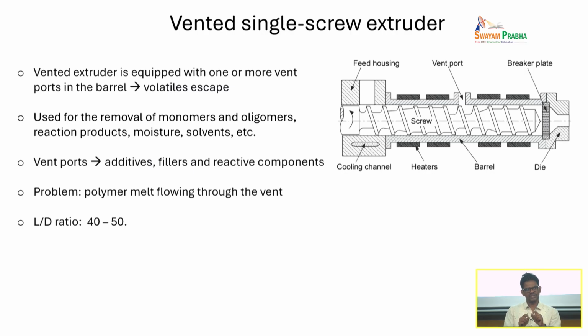So you need to have some provision in which you can actually let that vapor, the volatiles, go out. So that leads to the formation of these vent ports. Okay, so in this particular extruder, there's only one vent port, but you can actually have many of them. The idea is to see that you have a feed hopper here. Okay, so this is actually driven by a motor, and then you can see that this is the feed zone, then you have a transition zone and then metering zone. You can also see that somewhere here the diameter of the screw has changed, and then there is some gap here. So any volatile that has been created during the heating process of this section can now easily escape. Okay.